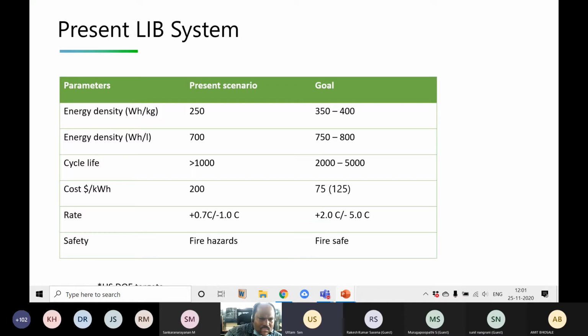Now look at the present status and the goal forward for lithium-ion cells. What we can expect in the next few years. The present energy density is 250 watt-hour per kg, and the expectation is 350 to 400 watt-hour per kg. That is the US DOE target, not the target from India. Volumetric energy density currently is 700 and the target is 750 to 800. Cycle life currently is slightly more than 1000.